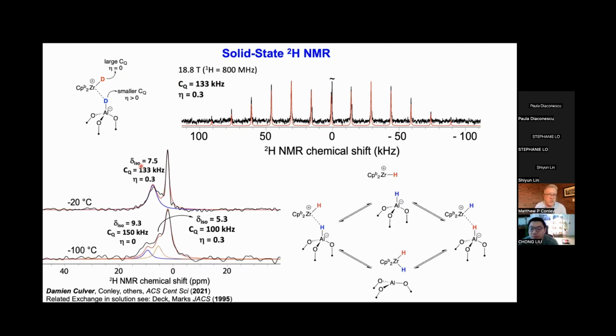So it took a while for us to do this because of the COVID lockdowns, but when we finally got NMR time to do this up at EMSL at minus 100 degrees, you can see this peak here, which is the composite of these two signals. We cool to minus 100. We split these into two signals, as you would expect. One at a chemical shift that is absolutely consistent with a zirconium hydride cation with a large CQ and eta of 0, and the other consistent with an aluminum deuteride anion with a smaller CQ with an eta that is greater than 0. That indicates that these two deuteriums are undergoing chemical exchange.